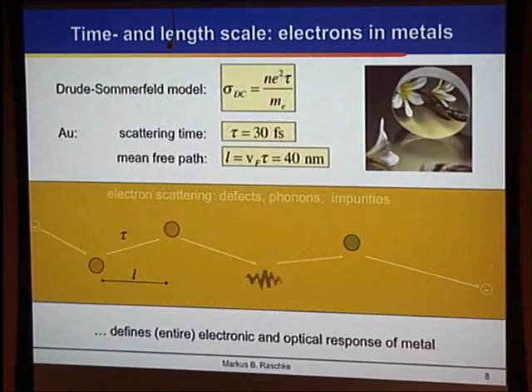To illustrate this, it is a good example to look at what is responsible for the reflectivity of a metal surface, and what the microscopic elementary process responsible for this is, to tell you how length and time scale are really correlated. If you take the Drude-Sommerfeld model for the conductivity of a metal, then from the electron density you can get an estimate of the scattering time, which is responsible for the finite resistivity of the metal.